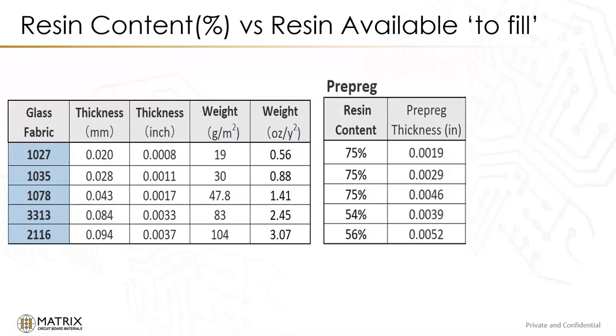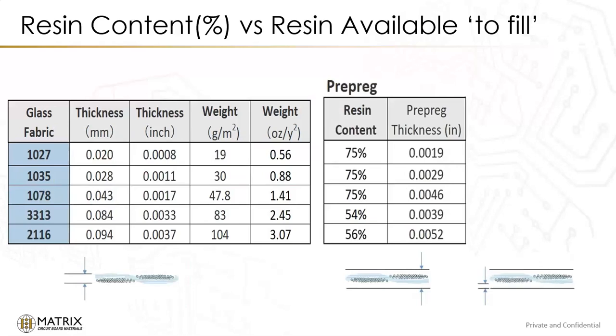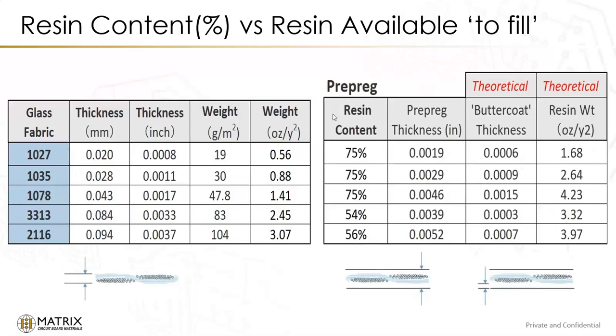But we have this prepreg thickness, so we know this dimension from top to bottom as a theoretical thickness on average between 2 solid copper planes. And if we know what the glass thickness is, that will help us. I came up with a way to quantify what would be a theoretical amount of resin on either side of the glass for each of these. And it makes for a very interesting table here.